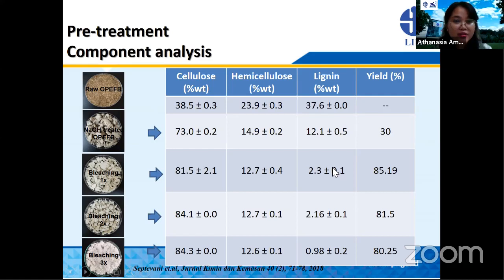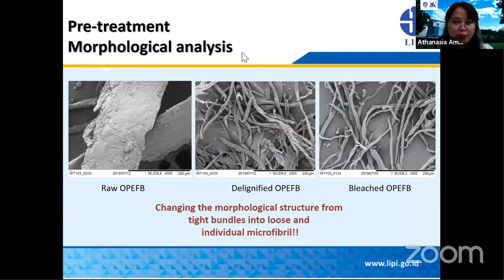So this is the result of the pretreatment of the biomass. We can see that the cellulose content is significantly increased in purity from 38% to 84% after the subsequent processes of delignification and bleaching. While for the lignin, it is reduced significantly from 37% to below 1%. As you can see here in the pretreatment morphology analysis, there is a distinctive change of the raw oil palm empty fruit bunch, based on the SEM, into individual microfibrils getting loose from the bundles of fibrils in the raw material.